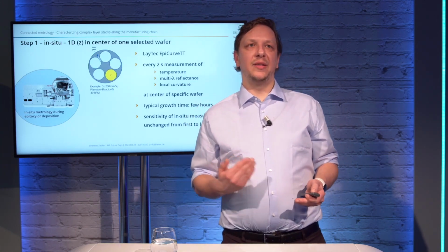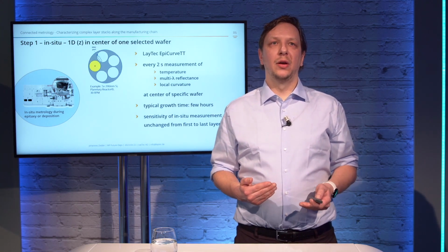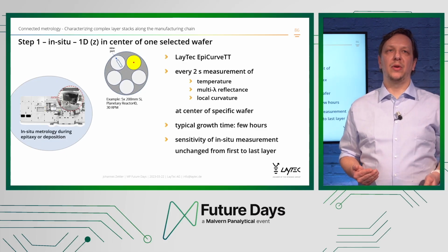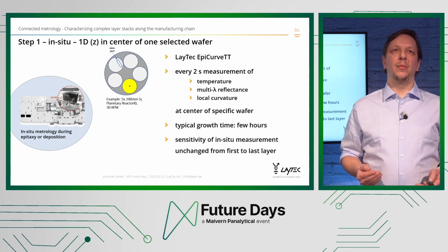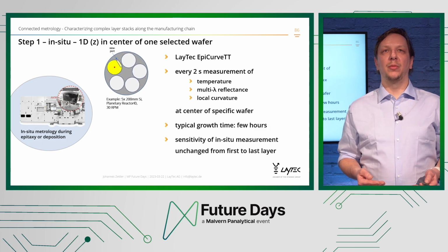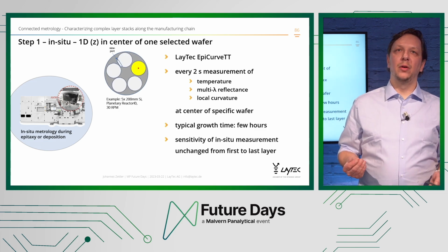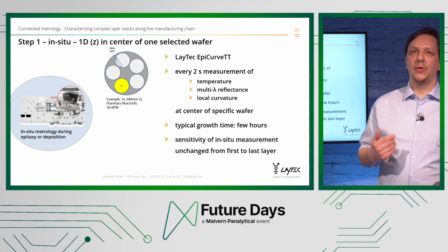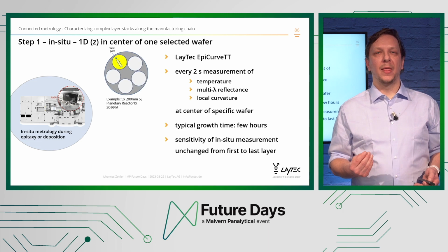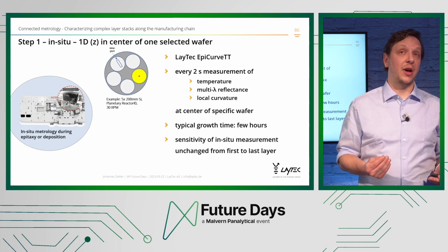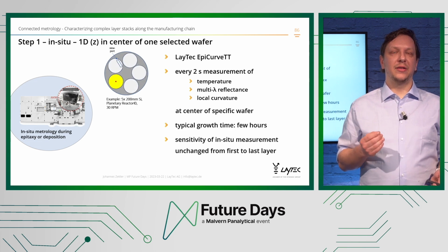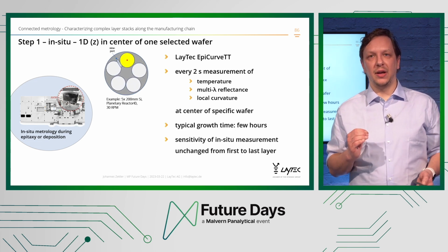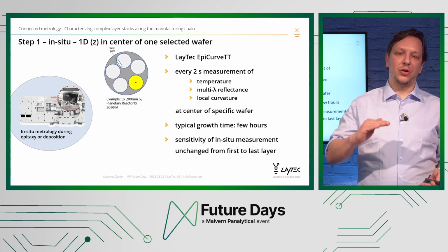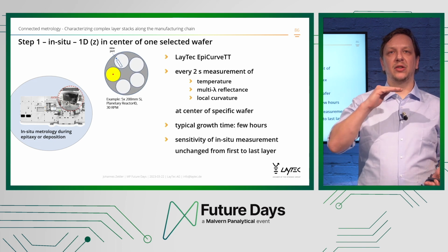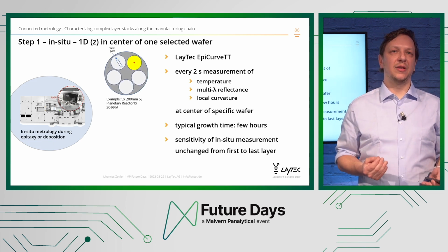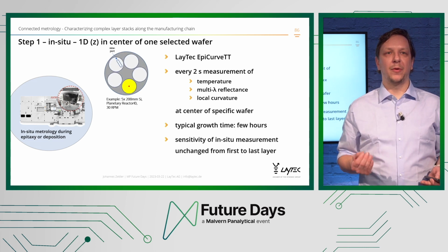So step 1 is in situ metrology during the epitaxy. In a typical planetary reactor, here we see a 5 by 200 millimeter silicon reactor, the wafer passes our optical metrology every 2 seconds. So in the wafer center, we have every 2 seconds a measurement of temperature, a measurement of reflectance at multiple wavelengths, and of the local curvature. As a typical growth time takes a few hours, we collect lots of data. And the important information here is that as we're measuring during growth, we're always probing the currently upmost layer, and thus our sensitivity of the in situ measurement is unchanged from first to last layer.